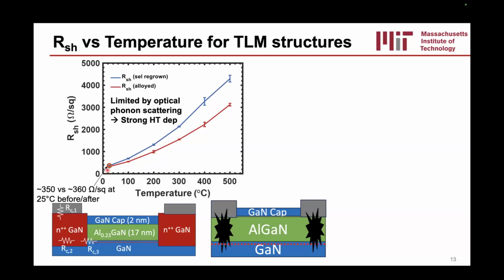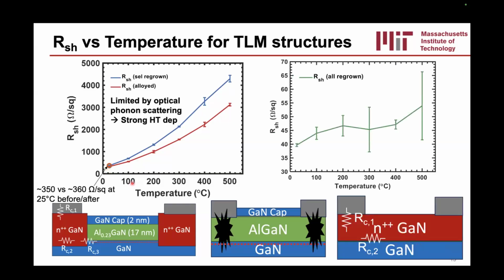Interestingly enough, we can also measure these highly doped GaN structures instead of the 2D electron gas structures. And we can see that the sheet resistance as a function of temperature does not change much at all. That's mostly because it's limited by ionized impurity scattering, or dopant scattering, which has a relatively weak temperature dependence compared to the phonon scattering we see in the 2D electron gas.